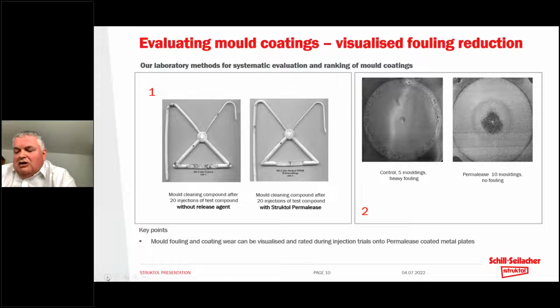And that's because the mold coating has provided an inert, resistant surface onto which the mold deposits are unable to adhere, and the deposits are simply removed with the molding. So in terms of the durability, the coating is quite long lasting. We can see a number of cycles without any breakdown and without any fouling. And of course, this gives us the opportunity to extend the workable time of the mold between the need for cleaning.